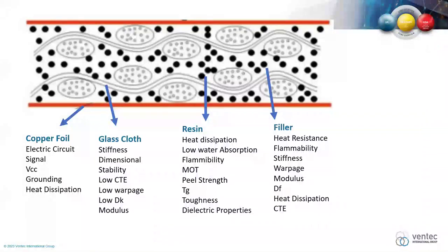A lot of the fillers we use are for heat resistance, flammability, stiffness, warpage, modulus, and basically loss of the material, again, heat dissipation, CTE. So in the ideal world, I would give the designer everything. The lowest CTE, the most thermally conductive and the best electrical properties. But unfortunately, some of these fillers act against each other. So we can't give you the best electrical and the best thermally conductive materials just based on the different types of filler. Some of the thermally conductive materials will have up to an 85% filler content. So they're pretty fragile. And a lot of those thermally conductive materials, because they're so fragile, fabricators are unable to handle them as a B-stage.